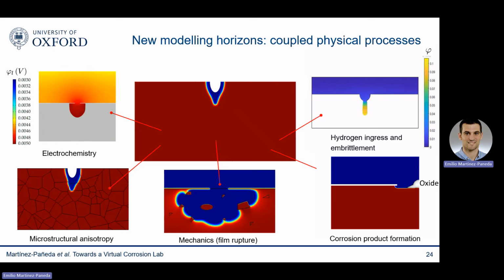As I said at the beginning, my friend claims that corrosion is too complex to be simulated with computers, and he might be right. There's many things happening and all playing a role and all coupled. But all of that physical phenomena can be simulated in a computer nowadays. We can incorporate the role of electrochemistry, the role of microstructural anisotropy, the interplay with hydrogen ingress and embrittlement mechanisms, the coupling with mechanical fields, which can disrupt the passivation film and also enhance corrosion kinetics, and the electric double layer and the formation of corrosion products, and others.